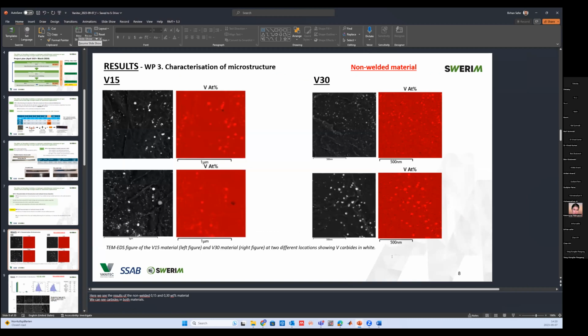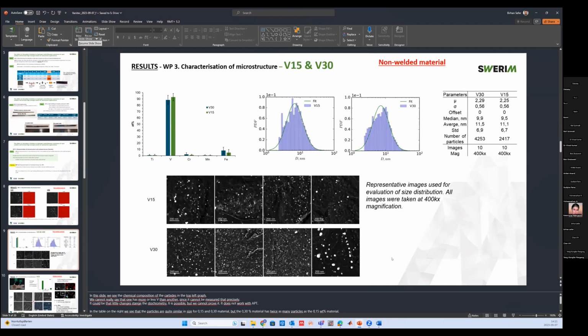So this is just to illustrate that we indeed have carbides, or vanadium carbides, present in the vanadium added steels. V15 and V30 refer to 0.15 and 0.30 weight percent. You can see on the micrographs and also on the EDS pictures that the carbides are present. This is the result for the carbides in non-welded materials, so as-processed material, where we can see that the carbides basically have similar size regardless of the content, about 11 nanometer. Unfortunately we are not able to discuss the number density, but locally we could see that the higher amount of alloying with vanadium resulted in a higher number density compared to V15, for example.